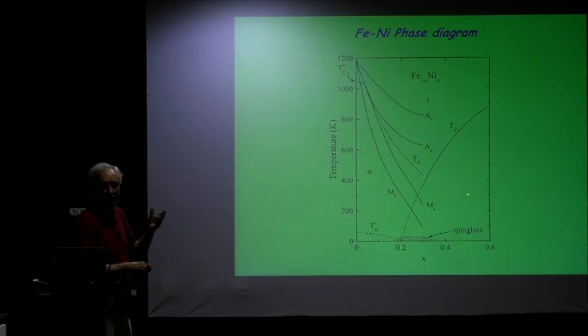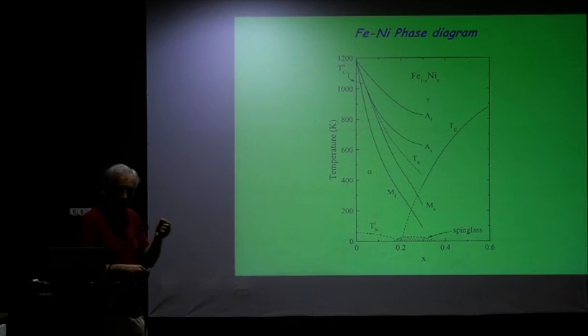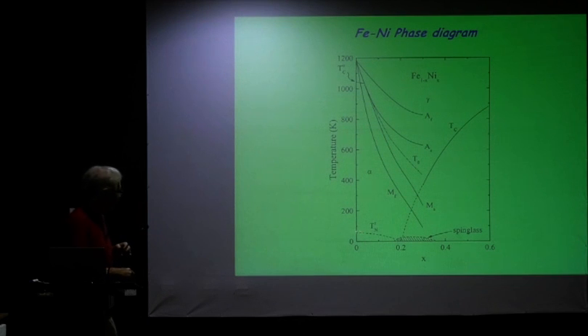We call that martensite. It's not iron carbon martensite. It's not tetragonal. It's still BCC in this case, but we still call it martensite. Yeah. And then when we go back up, there is this huge hysteresis of about 200 Kelvin, which has to be overcome when you come up here. When you are in the FCC state, after this composition, everything is stable. So everything here is face-centered cubic. The INVAR composition lies somewhere around 35%. That's around here. And the Curie temperature of the FCC state goes down like this. And the Néel temperature of FCC iron, which you can actually measure by stabilizing films, is around 70 Kelvin.